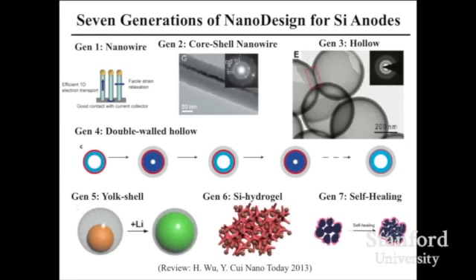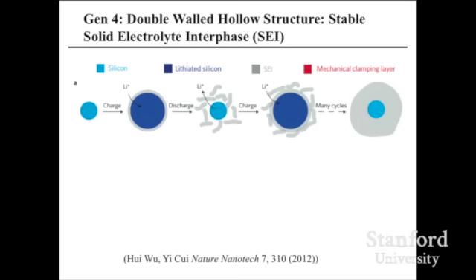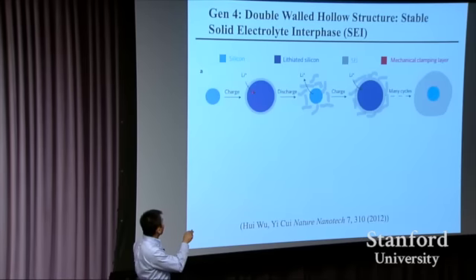Let me show you what the remaining critical problem is. It's actually the solid electrolyte interface. Our understanding has been that if you make the particles small, they don't break, so the breaking problem is solved. But what about the solid electrolyte interface? If you have a silicon particle, even if it doesn't break, when you put lithium in, it expands. It's going to react with the electrolyte, forming this SEI layer. If you take lithium out, it shrinks. This surface is not stable. This surface coating will be broken. And then you charge it up again, and you reform the SEI.